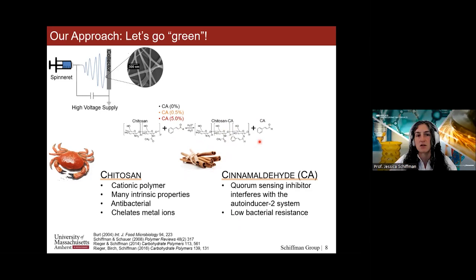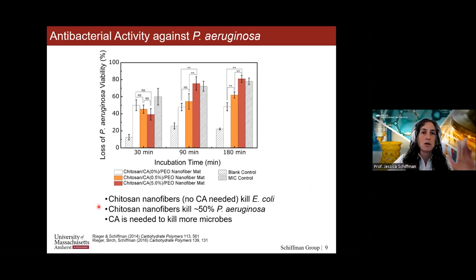And just one figure. So here, what I am showing you is how many Pseudomonas aeruginosa die as a percent as a function of incubation time. And so as you can see, here we have a blank control, meaning nothing's there. And then these middle bars are showing chitosan alone in white. So even chitosan alone kills about 50% of the Pseudomonas. However, when we increase the amount of cinnamaldehyde, these colorful bars, we actually have an increased amount of killing of the Pseudomonas.